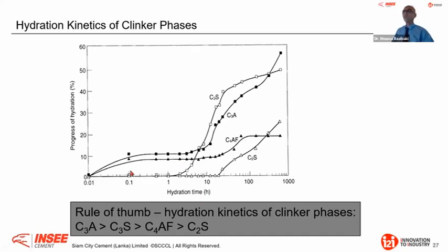Now, when I look at the progress of hydration, in terms of the hydration kinetics, you see the first 3 big elements, and as hydration is exothermic, it develops heat. Therefore, you see at a very early age, most of the heat will come from the aluminate phases, especially C3A, and after that, from 10 hours to 1 day, from the C3S. Therefore, automatically when you look at that, you all agree with me now that we need to limit the amount of C3A, the amount of C3S when we are talking about OPC based.